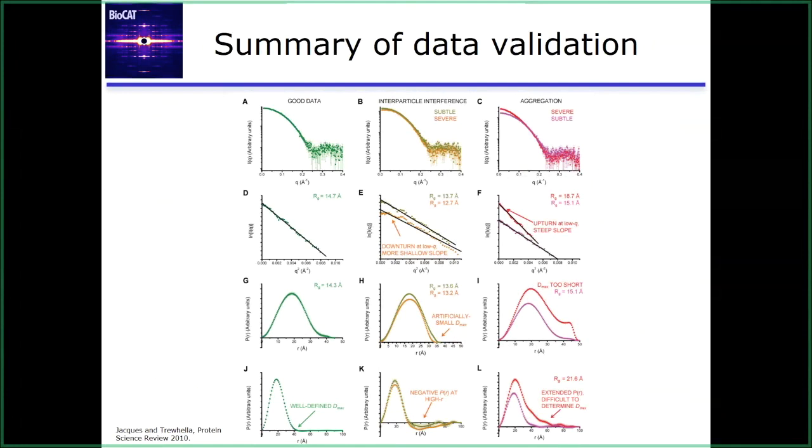Once you get a good fit in the limited range, then extend it out further and see if the RG changes and if the residuals go nonlinear or non-flat. Kind of more concretely, to get a Guinier fit, you have to do it iteratively. You pick a point, you get the RG, you calculate the Q max times RG of that point, you see if you need to pick a point that's further in or further out, and you iterate on that until you come to a solution. The software does a lot of that iteration for you, but you usually have to fine-tune the endpoints a little bit.